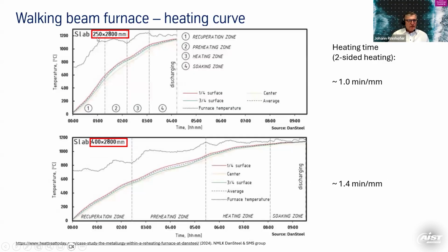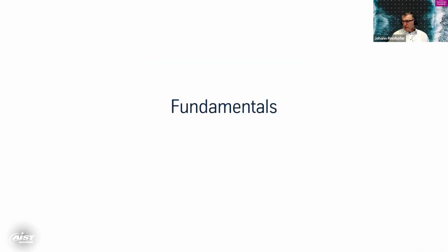How do you heat a 250 mil slab in comparison to a 400 mil slab? You see the difference is the heating time, obviously, but everything else is very much the same. So in the end, you end up with 1 minute per millimeter or 1.4 minutes per millimeter thickness of slab when you just look at it in average. So this 1 minute per millimeter is a typical specific heating time for, say, 200 mil slabs. Let's go into the fundamentals.